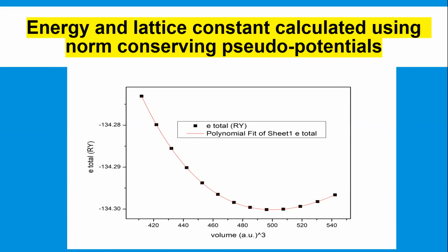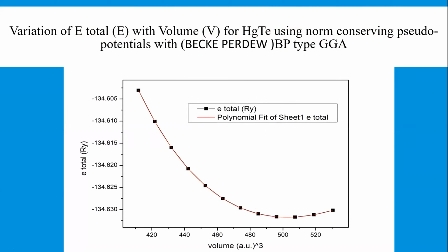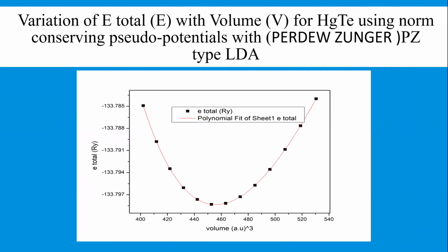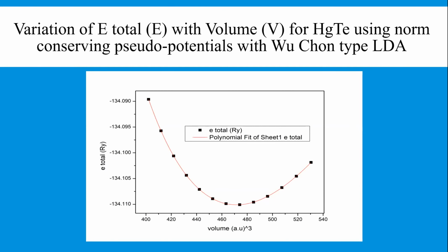This is my work, in which the energy and lattice constant are calculated with the norm-conserving pseudopotential. We obtain the lowest energy in this region, up to 495 volume. We can get the optimum volume and the corresponding total energy, that is minus 134.30 Rydberg. The present slide also shows the variation of mercury telluride with lattice constant and total energy cutoff. We can further say there is a whole set of results obtained by using various kinds of exchange and correlation functionals, sometimes LDA and GGA. These results suggest the final result.